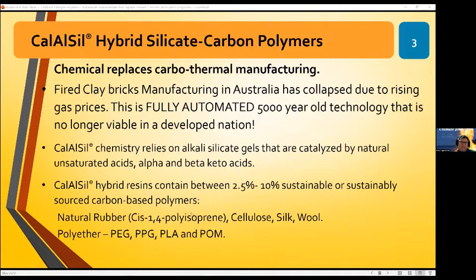The hybrid resins, so I use natural rubber, cellulose, silk, wool, also polyethylene glycol, polypropylene glycol, polylactic acid, and polyoxymethylene. So essentially polyurethanes are also excellent hybrid polymers. So really I could go down to the local hardware store, grab a timber varnish, and mix it in with my CalAlSil resins.